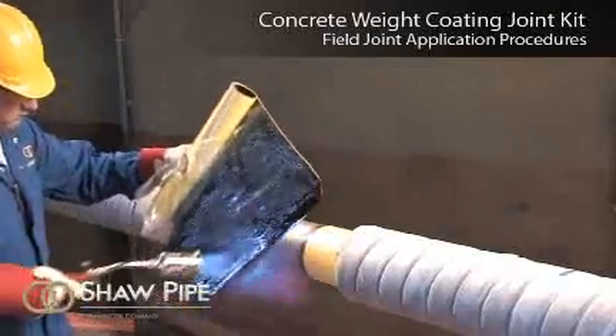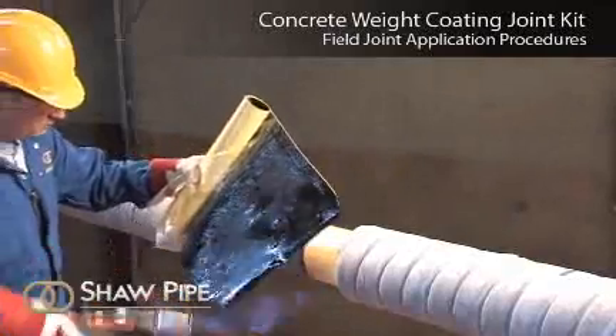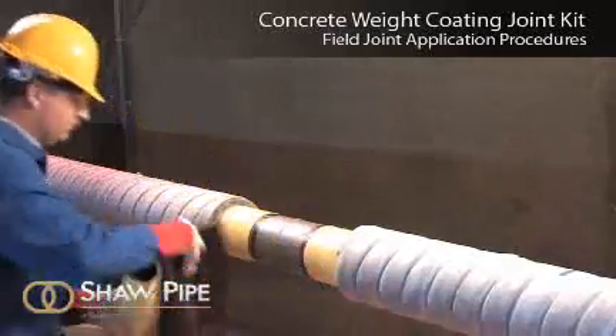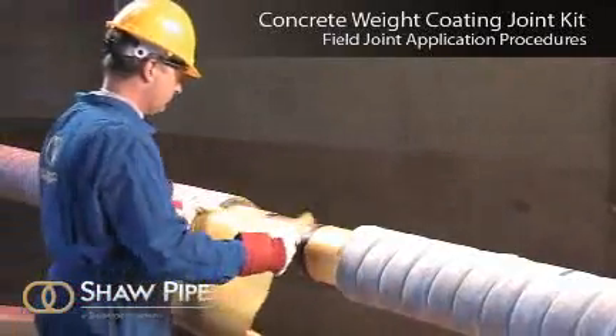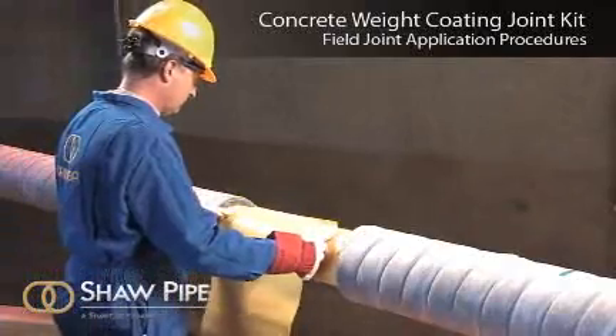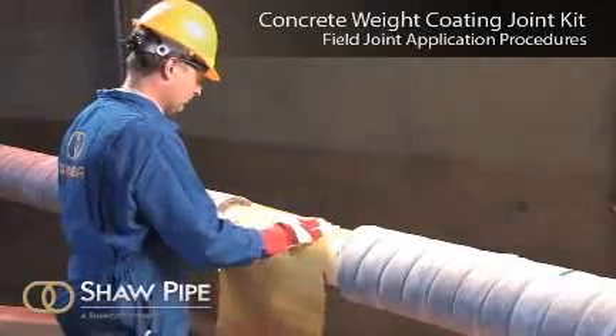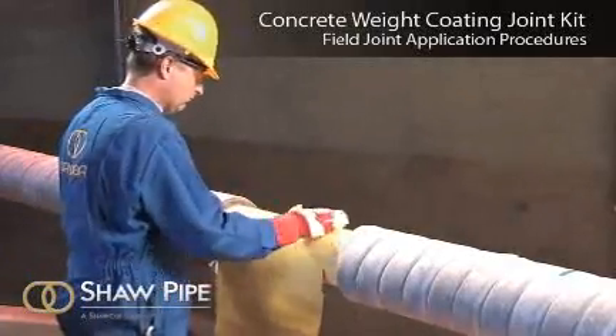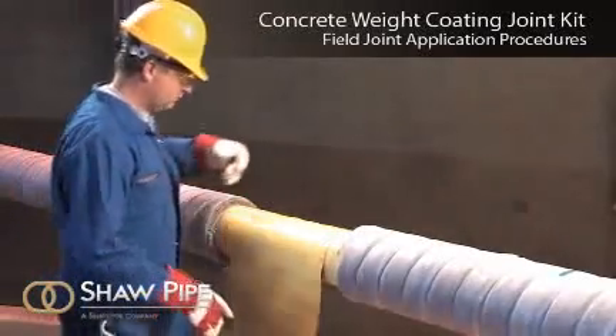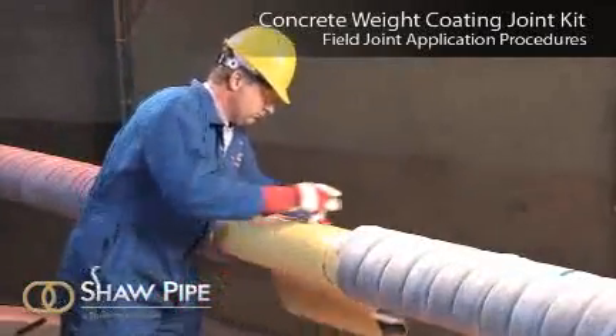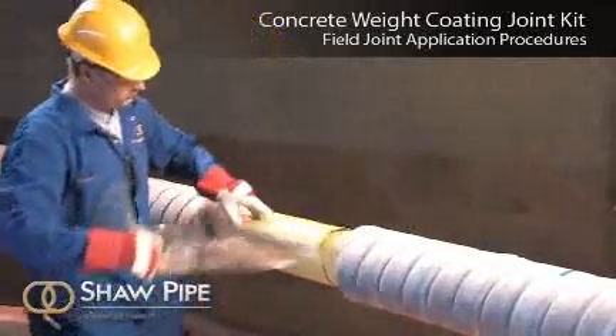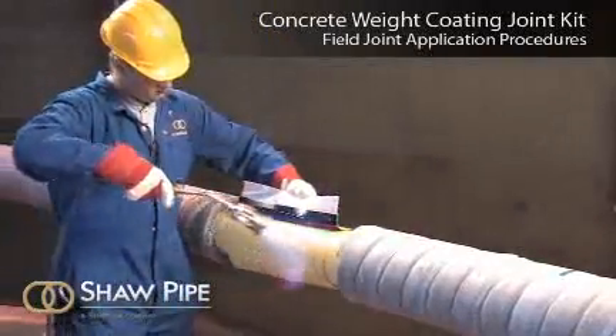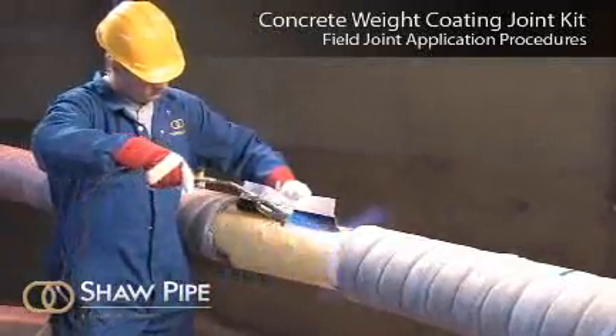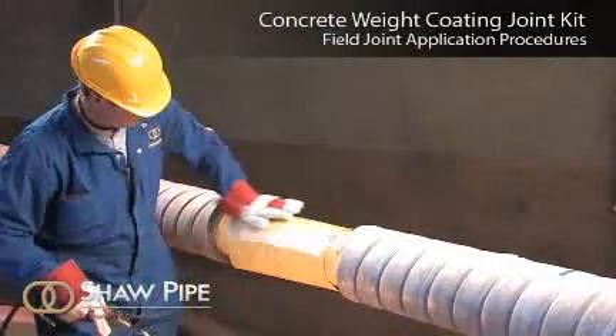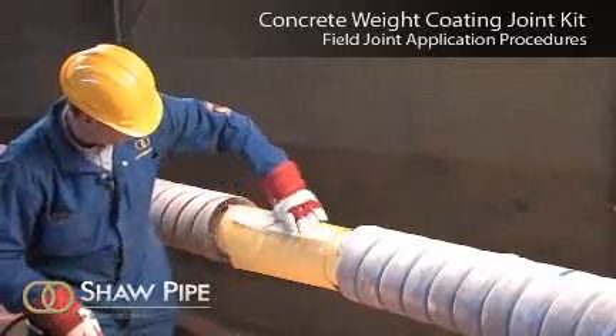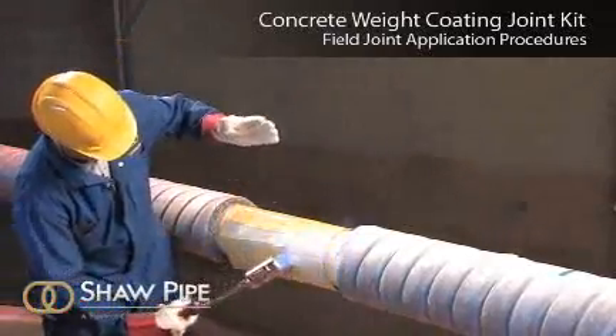Partially remove the release liner and lightly heat the underlap at the edge. Center the sleeve over the joint so the sleeve will overlap between the 10 and 2 o'clock positions and press the underlap firmly into place. Remove the remaining release liner while wrapping the sleeve loosely around the pipe. Gently heat the backing of the underlap and the adhesive side of the overlap and press the closure firmly into place.